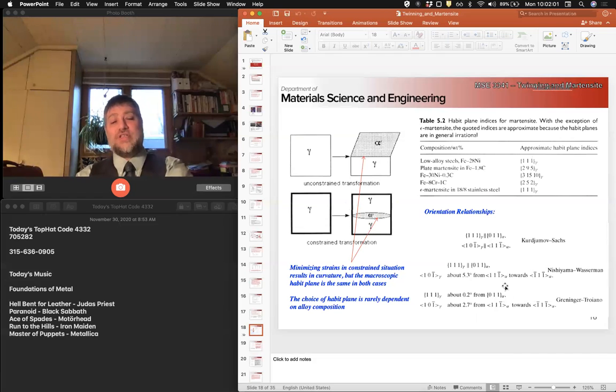The orientation relationship in carbon steel is generally quoted as the Kurdyumov-Sachs, which has the close packed directions parallel with each other, right? In iron nickel, we see a relationship that's called the Nishiyama-Wasserman. And then we have a whole family of orientation relationships called Greninger-Troiano, which are intermediate to Kurdyumov-Sachs.